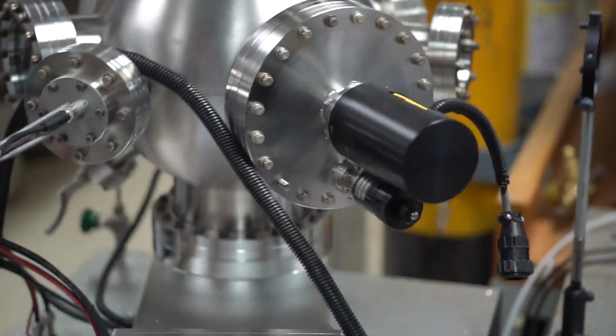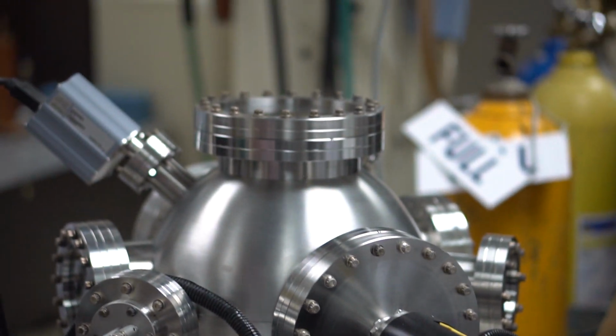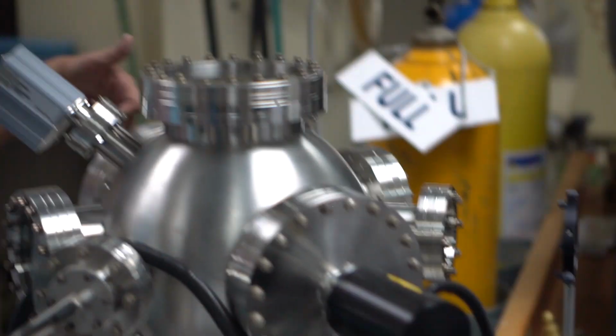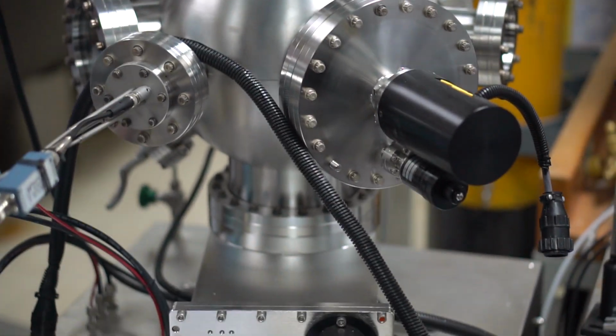The beam, which is Gaussian, you can say, has its maximum intensity in the middle. So the beam comes through this, we focus it, and we put the target here. And the target is rotating all the time. At one time, we can upload 6 targets. For example, we can put zinc, titanium, copper, silver, all of this, okay, 6. And they are rotating continuously. And on this side, we have the substrate on which we want to make the film. It is around a 2-inch distance, roughly, okay.